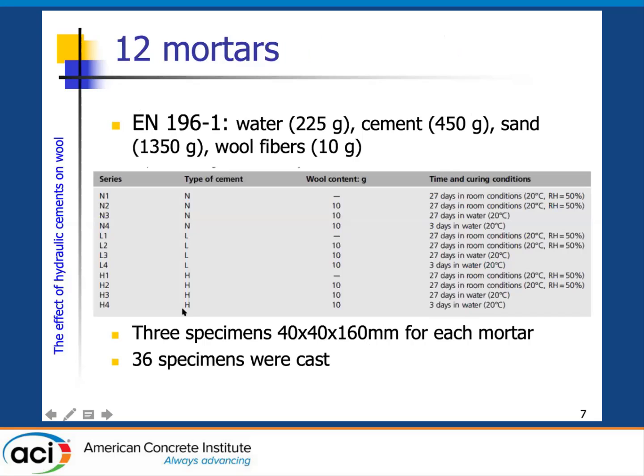We cast 12 series of specimens. As you can see, the first letter is related to the type of cement: normal content, low content, and high content of alkali. So number one is referred to specimens without any reinforcement, and they were cured in room conditions. The same is also valid for the L1 and H1 series.